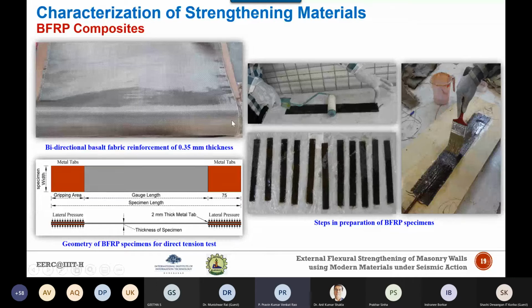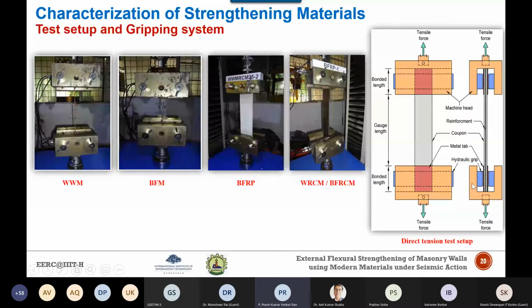Now let's come to the test setup and the test results. In the present study, clamp type grips have been provided to test the reinforcement and the composite specimens in direct tension. And the tensile force has been applied using specially designed grips in order to avoid any slippage. So this is my wire mesh specimen, fiber specimen, then the composite specimen, and then the FRP specimen. Now let's see the results.